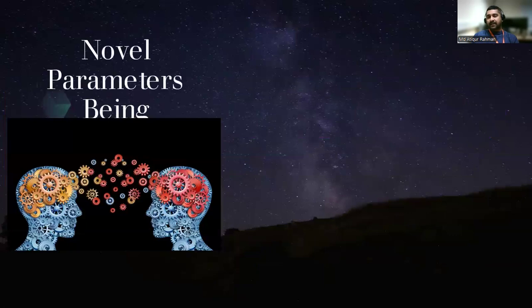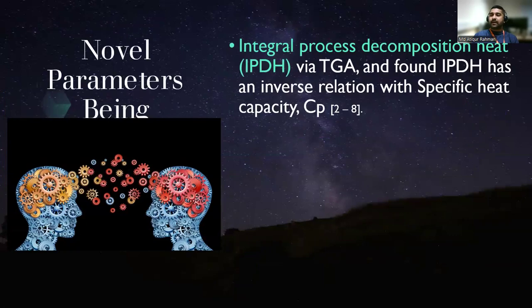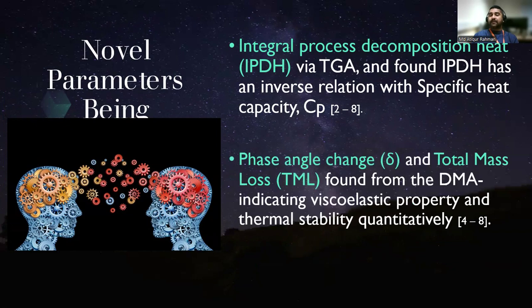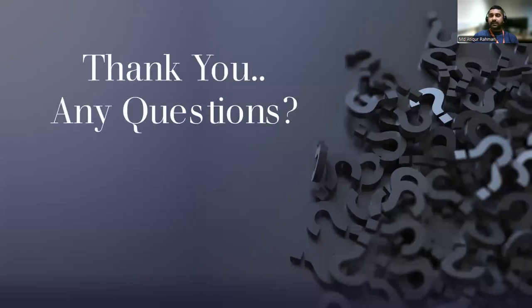Apart from that, as I said before, novel parameters we have found, one of which is the IPDH via the TGA. And we found that the IPDH value has an inverse relation with the specific heat capacity. And furthermore, from the DMA, we found the phase angle change and total mass loss, which can indicate viscoelastic property and thermal stability quantitatively.